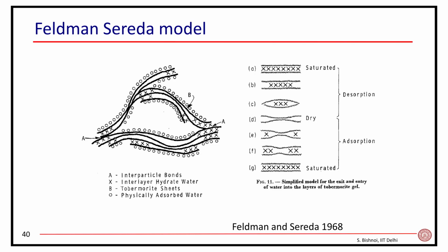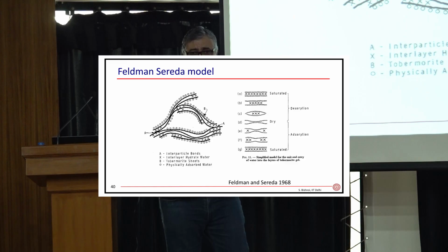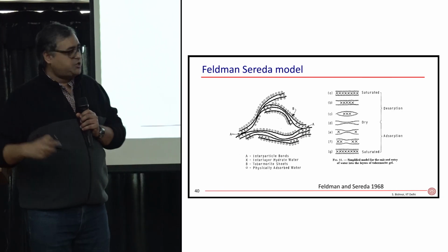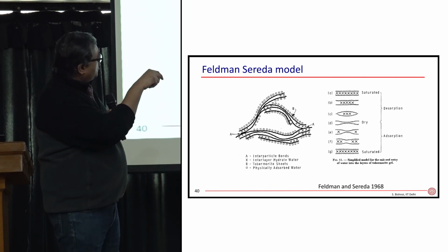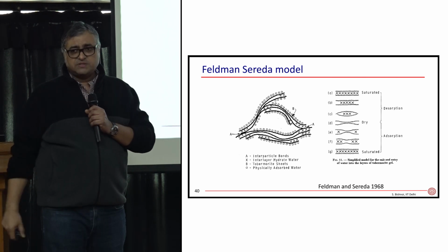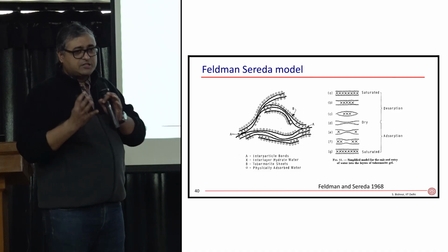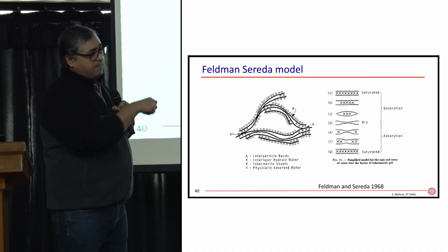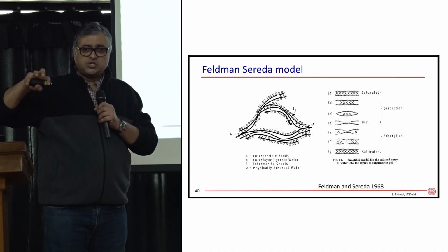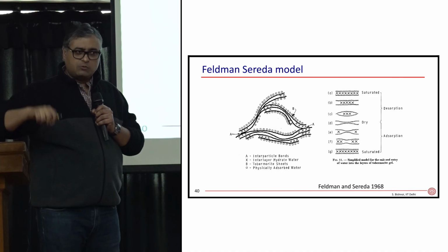Feldman and Sereda measured length change and weight change, and they came up with this model of CSH. They said inside that gel, water is present adsorbed on the surface of the calcium silicate sheets, between those sheets, holding those sheets together. In the pockets left behind between these sheets, there's water trapped inside, like that water balloon.